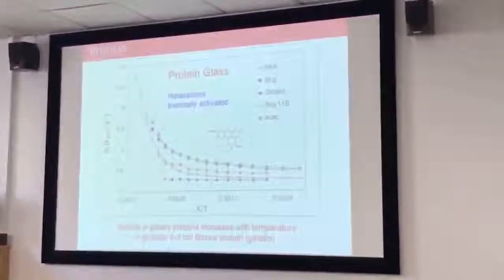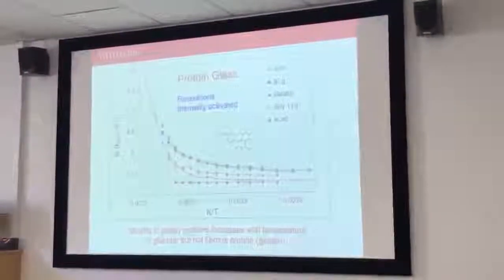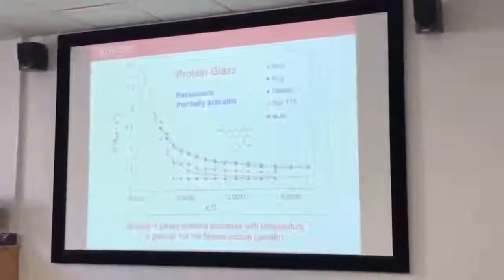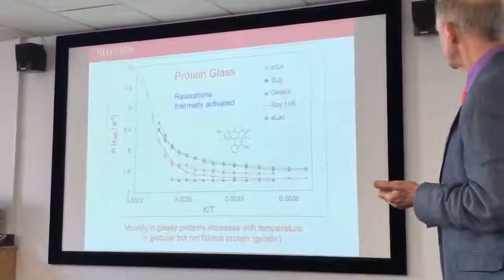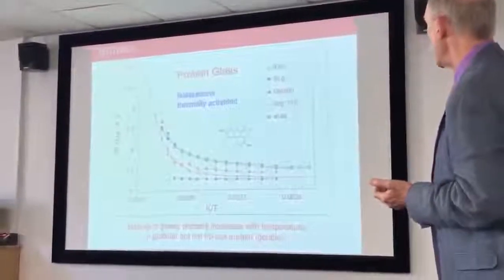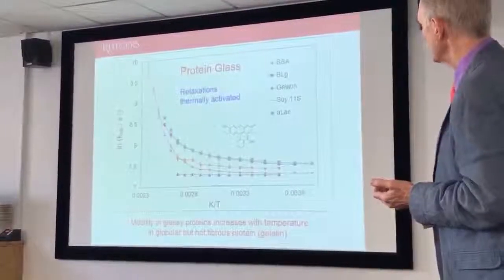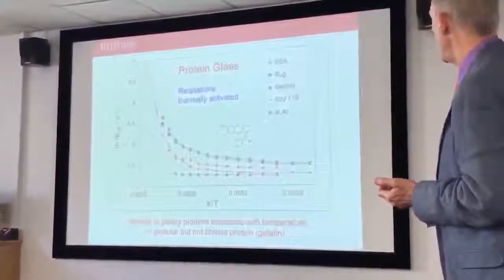Now I do not normalize it because the glass transitions are, well, I'm not really sure what that means for these proteins. But we do see one that's different. It's hard to see any variation within gelatin, but of course gelatin is radically different. It doesn't really have the kind of structure. This is made so that gelatin is actually amorphous. It's not triple helical when you make these samples. The others are globular proteins, but you get the same sort of increase in dynamics as you get to higher temperature. But the key thing I'm showing this data for is because I want to show you the oxygen permeability.